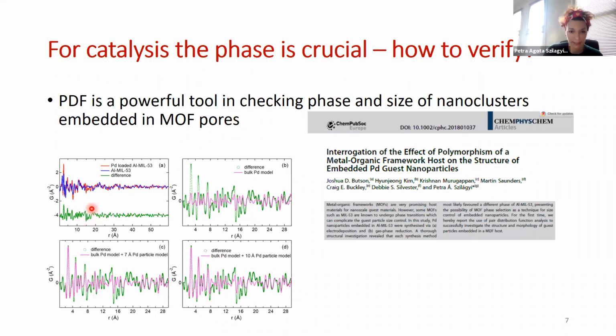So in this case, this is palladium, and this is what we got. You have it in green, and what I would like you to focus on is really the data set in green at the moment. The first thing that you should notice is that at higher interatomic distances, all we have is noise really. So the clusters are very small. And the second thing is that the positions themselves are very well determined. Although whether it's crystalline or not is more of a philosophical question, because there is no periodicity really, the atomistic structure is very well determined.